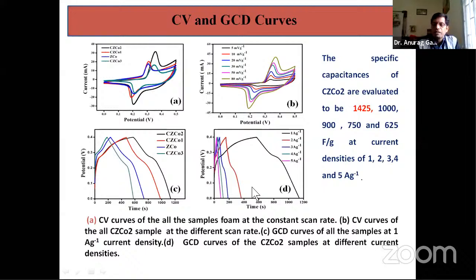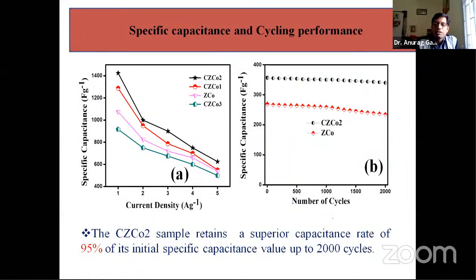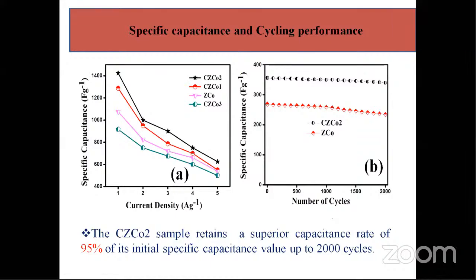So it clarifies it is pseudocapacitive, and for a single electrode, the capacitance is 1425 farad per gram. That is for a single electrode, not for the device. For the device, it will be one-fourth. So quite a good value of specific capacitance is observed. And in the cycling test, 95% of the specific capacitance is retained up to 2000 cycles for this material.